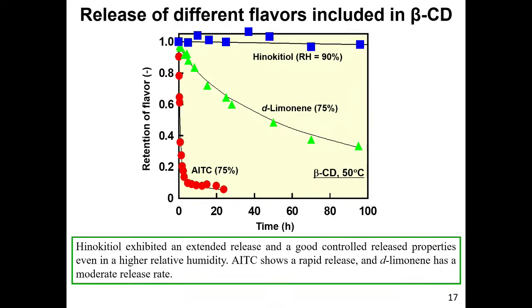So release of different flavors included in beta cyclodextrin: hinokitiol at 70 degrees, 70% relative humidity case, we cannot see the release. But AITC rapidly released.